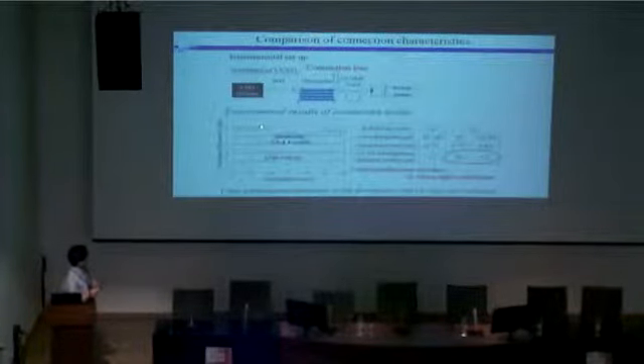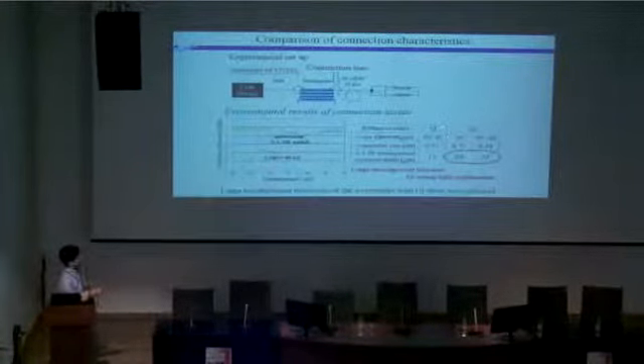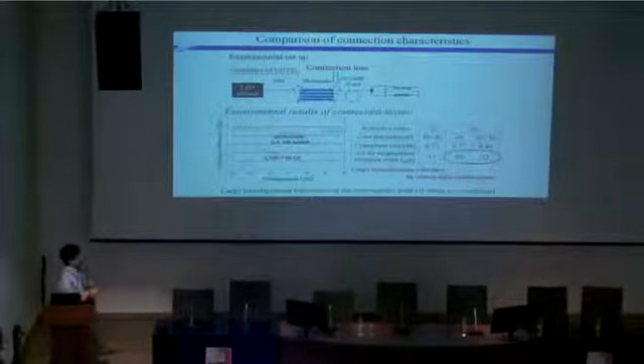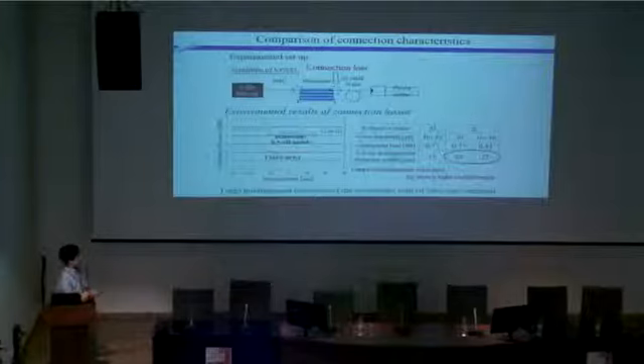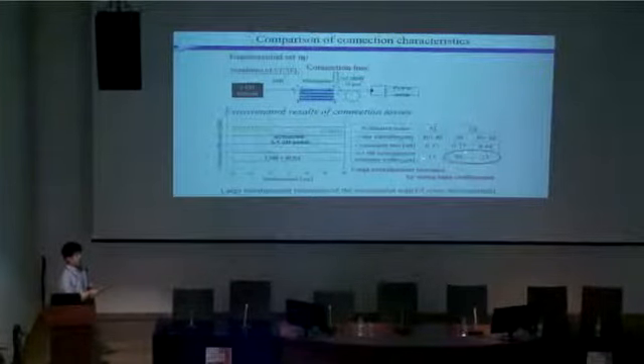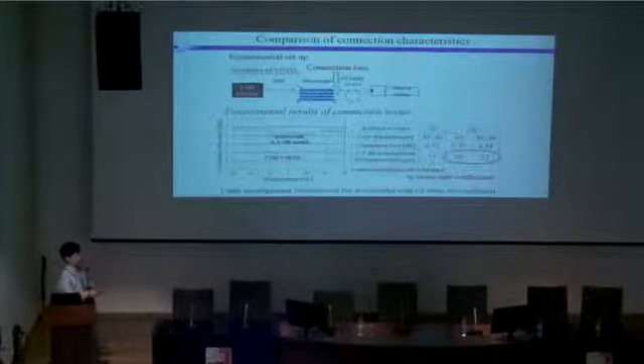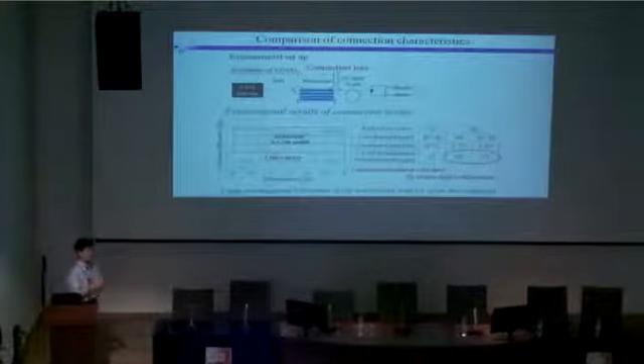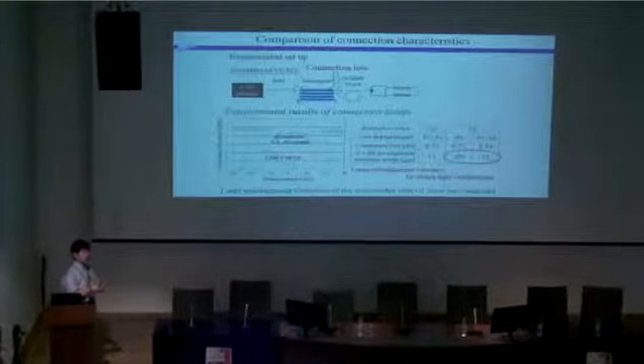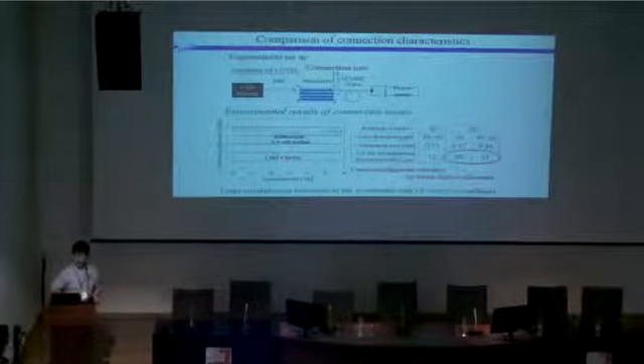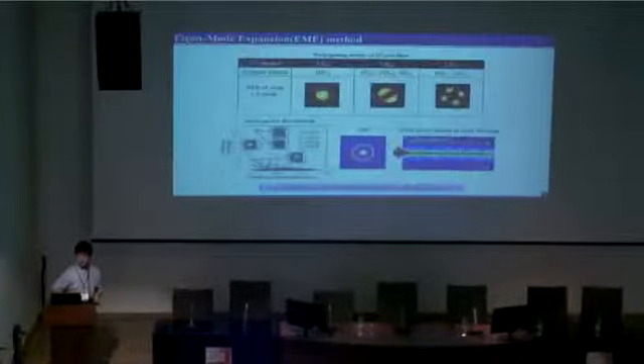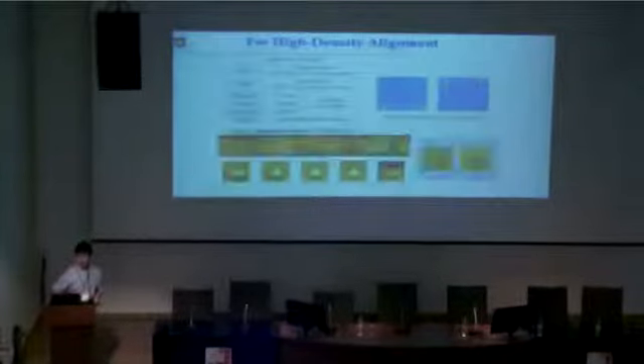Here, you can see, the 40 micron SI has a misalignment tolerance of 15 for 0.5 dB misalignment, while in the case of GI, the misalignment tolerance is wider than SI because of the difference of near field pattern. In the case of the SI core, the near field pattern is well spread out to the whole core.